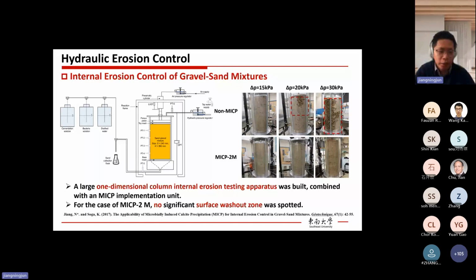So we designed a large one-dimensional column internal erosion testing apparatus, as you can see here, to accommodate the size of gravel particles. We made it with a diameter of 240 millimeters and height of 550 millimeters. So it's large enough to accommodate the gravel sand mixtures. Then we designed an MICP implementation unit, so the bacterial solution, cementation solution, and distilled water can be injected in sequence based on our need.